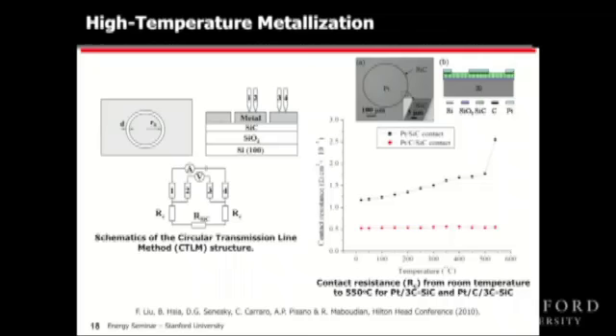So what about metallization? In addition to your sensors, you have to have the packaging and the electronics to go along with it. This is an image of a test structure used to study high temperature metallization on silicon carbide. Our first thinking is to use platinum because it's a high temperature metal. It's an inert metal. It operates at very high temperatures. And so if you position platinum directly on silicon carbide, unfortunately your contact resistance changes as you go from room temperature up to 600 degrees C due to generation of platinum silicides.